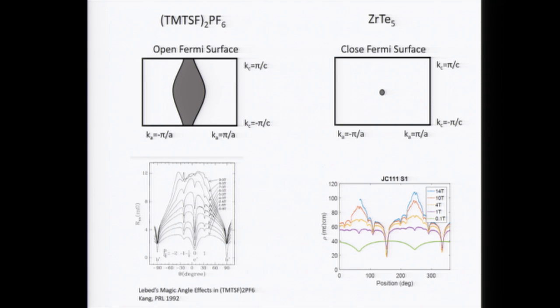So this is the Fermi surface that you kind of expect for this organic. But we're talking about a very small amount of electrons, a tiny Fermi surface that probably occupies just less than 1% of the Brillouin zone volume in the three-dimensional cell. So there's no way all this 1D traverse orbit could apply for this scenario. Instead, we now have Dirac electrons, high mobility, high magnetic field, and somehow the electrons know something of the underlying lattice.